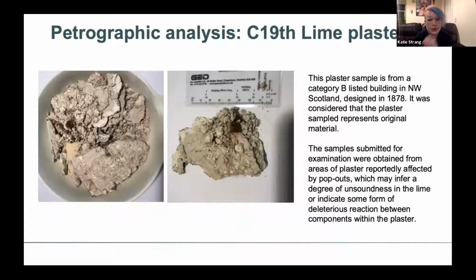So they were first sent to me because they had this really odd occurrence that this plaster had been in the ceilings for over 100 years, and all of a sudden it started slaking, what you get called pop outs. That's where you have those inclusions of lime that I was talking about before that haven't fully slaked with water. So if any moisture gets into your material, it's going to cause that reaction, and essentially it causes an expansion of the particle, and it'll pop out of your plaster.